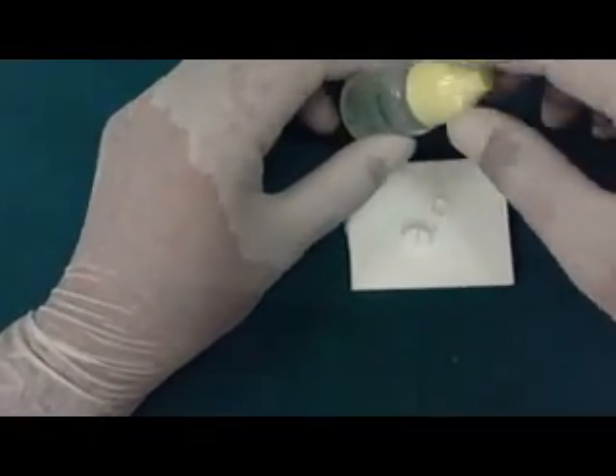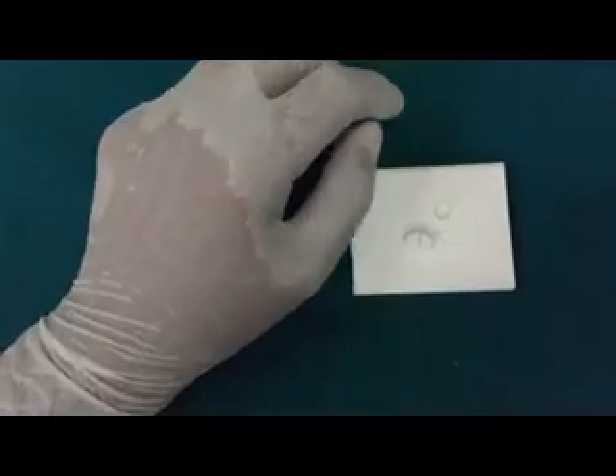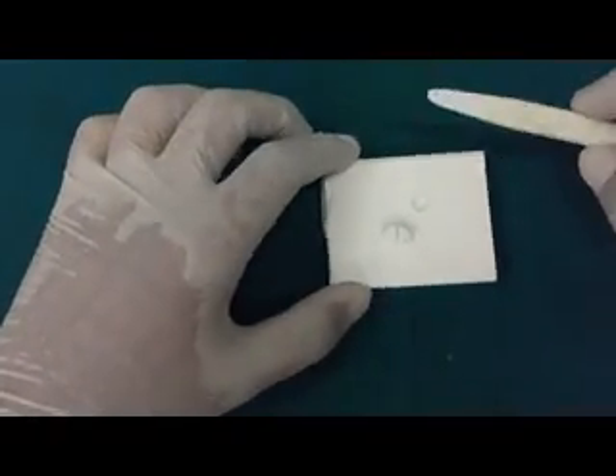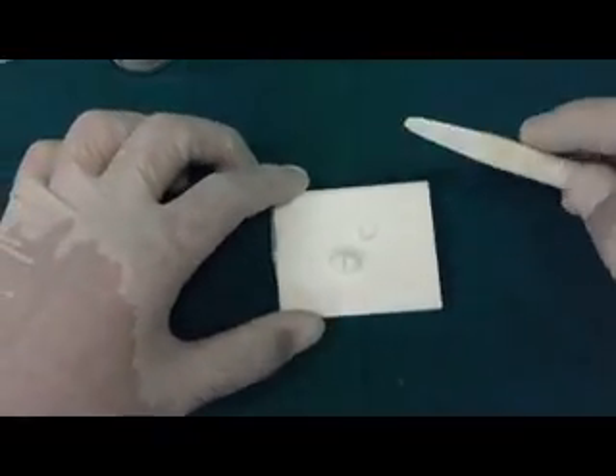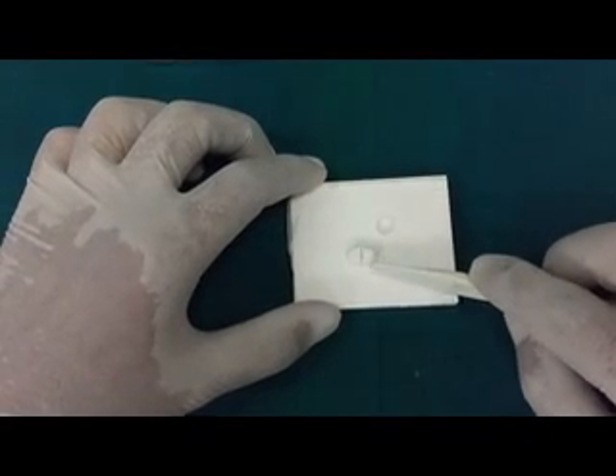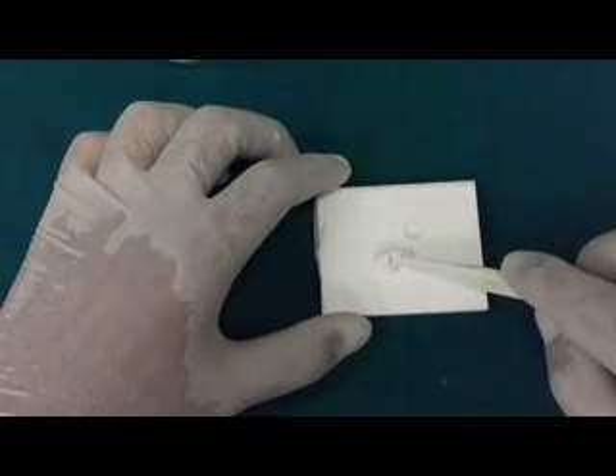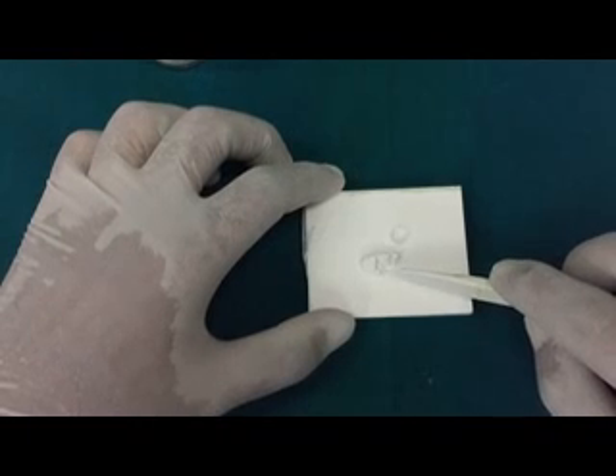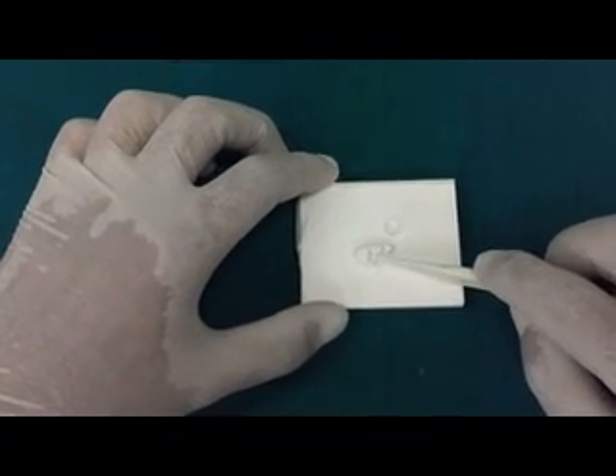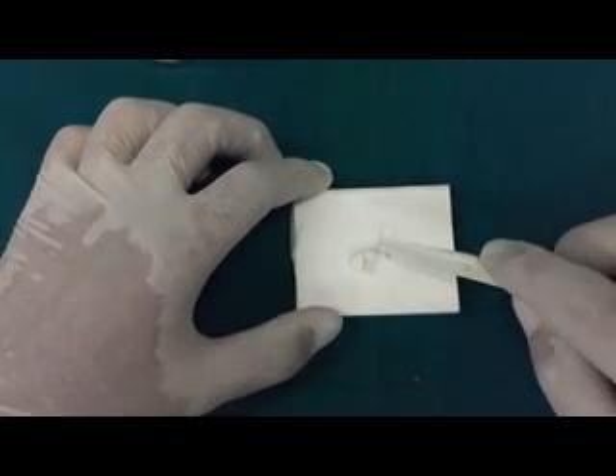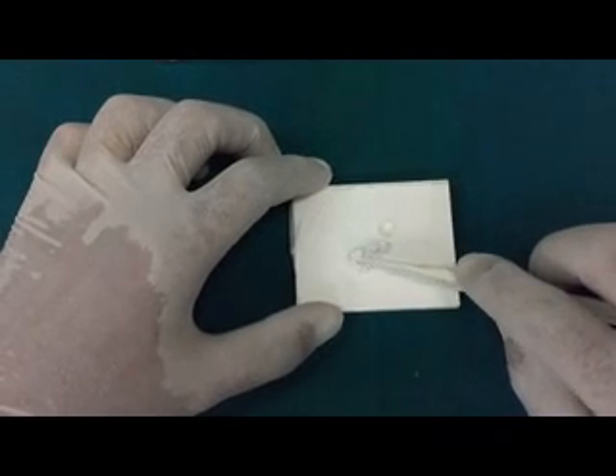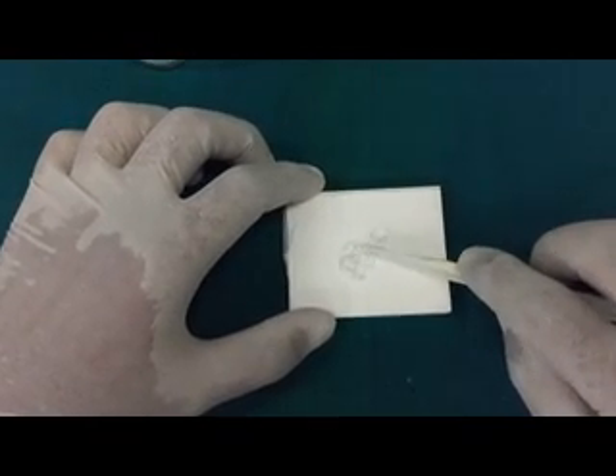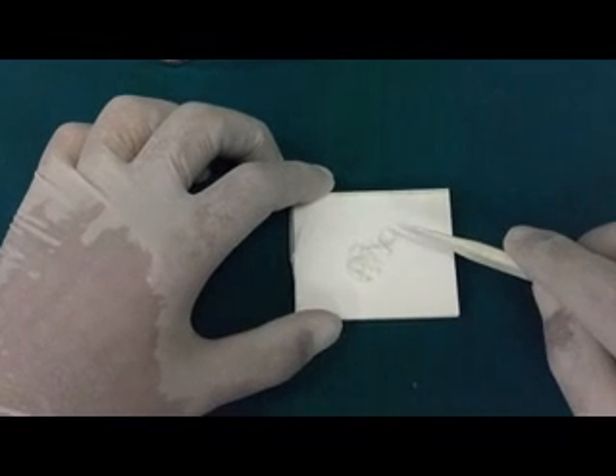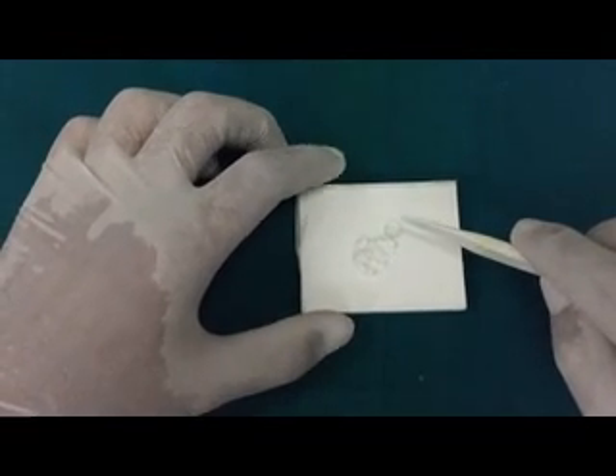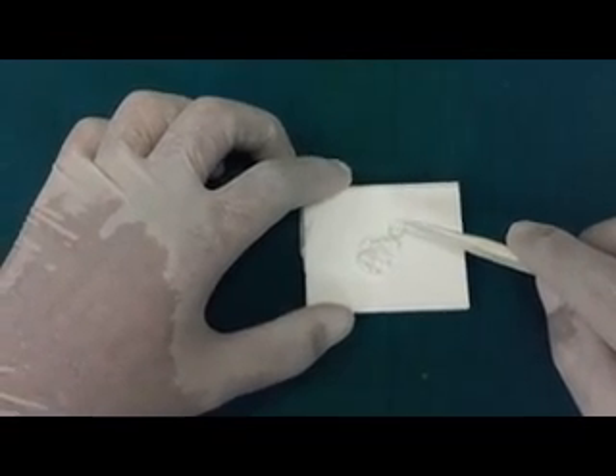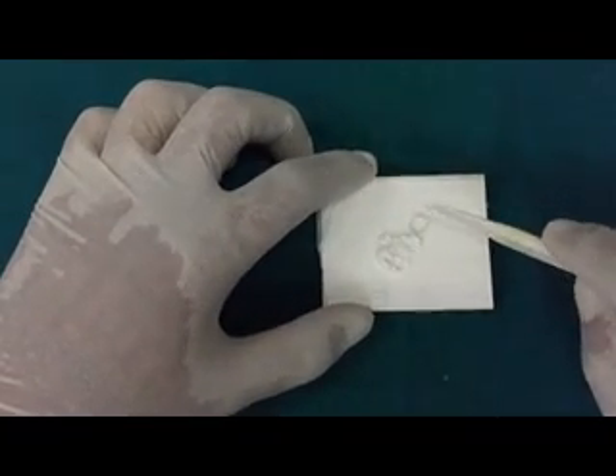The liquid should not be dispensed earlier and kept, because it will lose water, which is a very important component in the liquid. We have to dispense the liquid only at the time when we are going to utilize the material and not remove it and keep it on the table. Especially under Indian conditions where the temperature is very high, room temperature can easily evaporate the water content in the liquid, and that would definitely have an effect on the final properties of the cement.